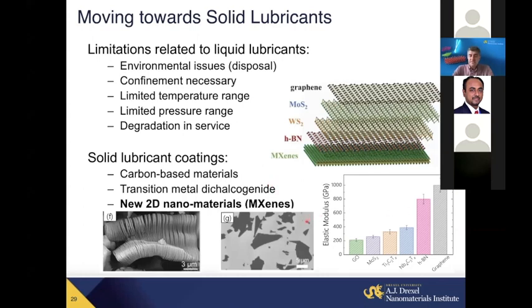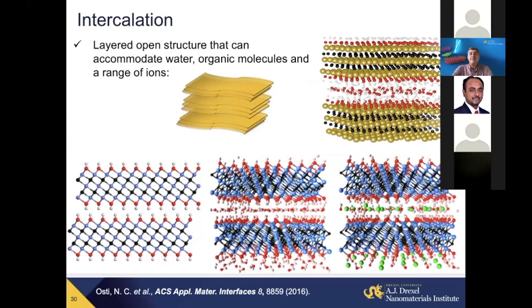It's not only the strength and mechanical properties I mentioned, and actually, just to add to this, niobium carbide MXene showed itself to be even stronger than titanium carbide. And if we make the materials more perfect, minimizing the number of point defects, vacancies on the surface and others, we can push the values of their moduli to the predicted values that I showed you in the table. But there are also their surface chemistries. When you look at these MXene flakes, they always have intercalated water layers in between, or you can replace water with organic solvents, with other molecules, or you can also add ions.